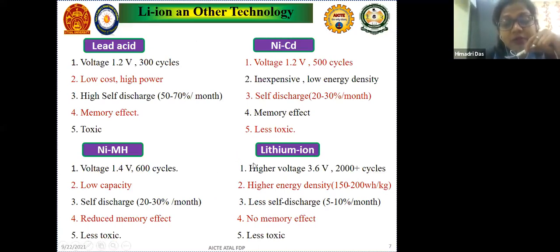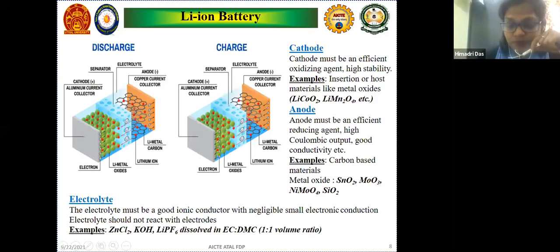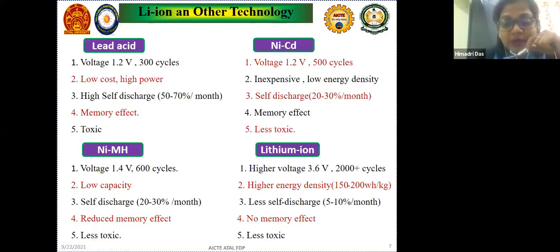So here now we have almost lithium ion battery, and we all are utilizing this battery because of its advantages like 3.6 volt and more than 2000 cycles with energy density of 150 to 200 watt hours per kg. And the most important factor is that it has very little self discharge and no memory effect. And it's also quite less toxic than other batteries.